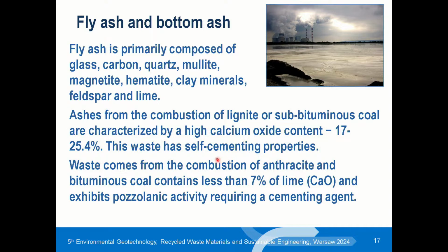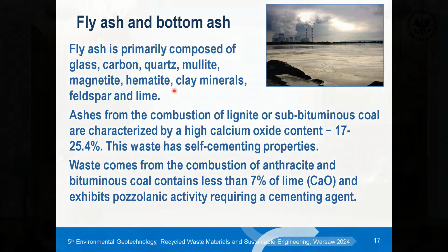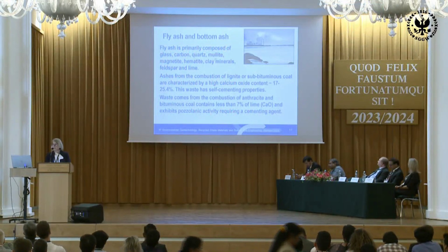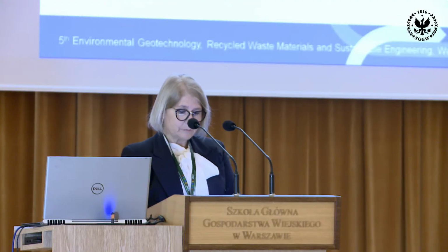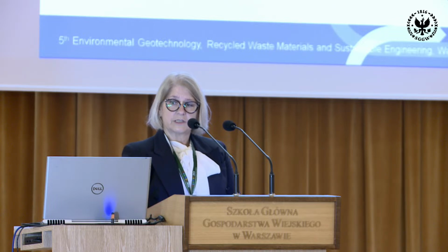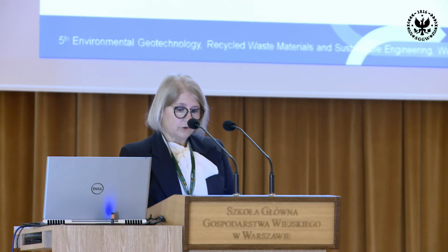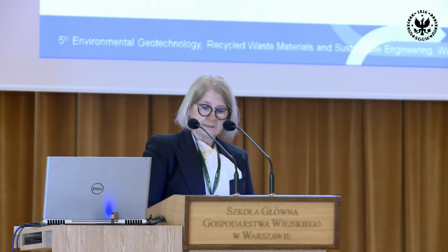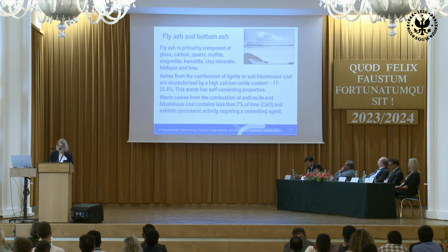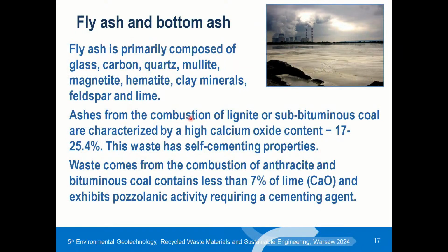The next is my favorite, fly ash and bottom ash, because I spent my whole life on research on fly ash. Fly ash is primarily composed of glass, carbon, quartz, mullite, magnetite, hematite, clay minerals, feldspar, and lime. And we should know that ashes from combustion of lignite or subbituminous coal are characterized by a high calcium oxide content of about 25%, and this waste has self-cementing properties.